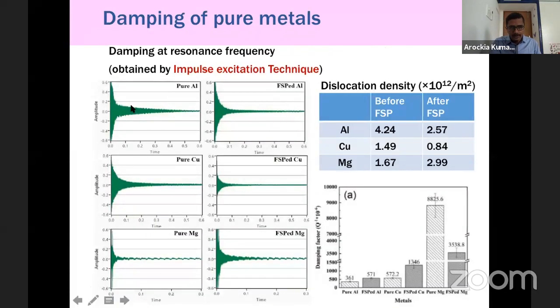All these graphs show the amplitude of vibration with respect to time, showing how effectively the material damps the vibration. In pure aluminium, it takes a very long time for the vibration to die. After FSP it is somewhat reduced, but not that evident. But in copper it is clearly evident: before FSP, pure copper takes a very long time to damp the vibration, but after FSP the vibration dies very quickly. So the damping property of pure copper is significantly enhanced by just one pass of FSP.